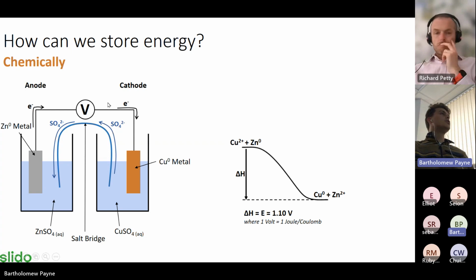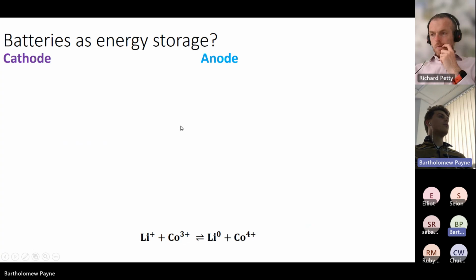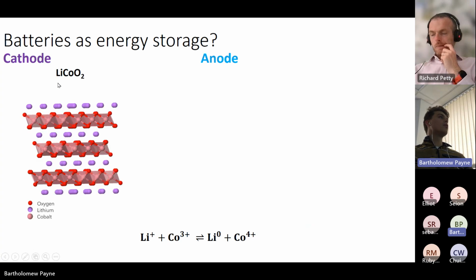So if we think about this image, this is basically a battery. As I said, this is the first ever battery, made by Alessandro Volta in the 18th or 19th century. So what does a more commercial battery like we use nowadays look like? Well, it uses two materials, one being lithium cobalt oxide, which has lithium 1+, oxide 2-, and then cobalt 3+. We know those are the charges because you've got 2 O2-, 1 lithium 1+, and therefore for charge neutrality, your cobalt will be 3+.